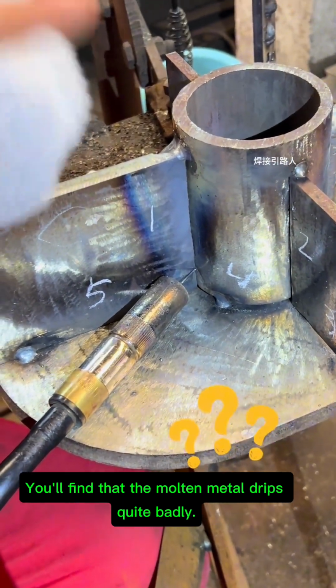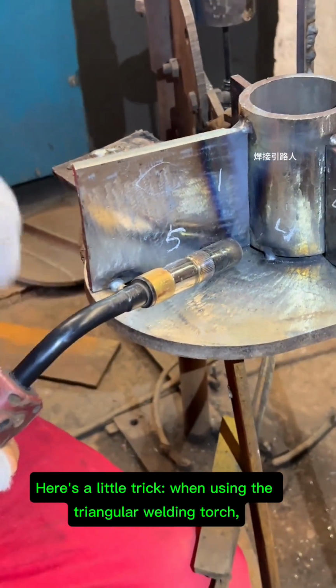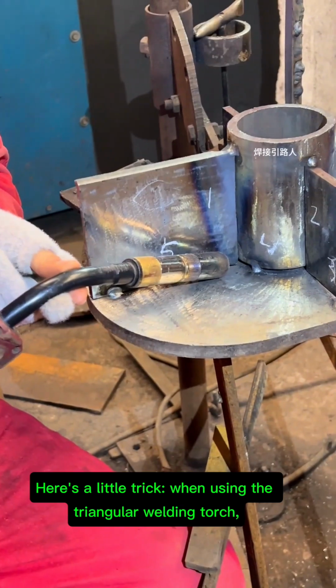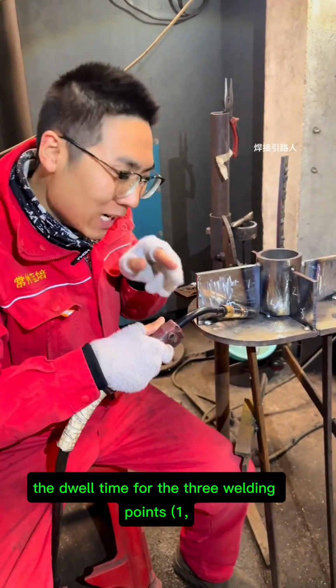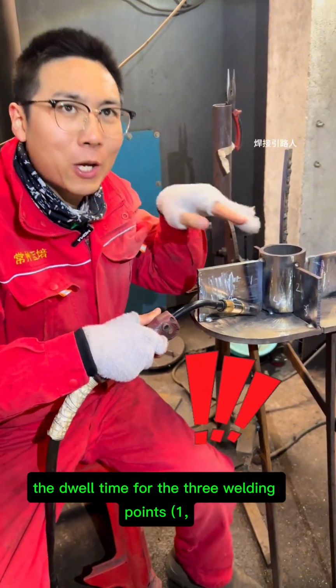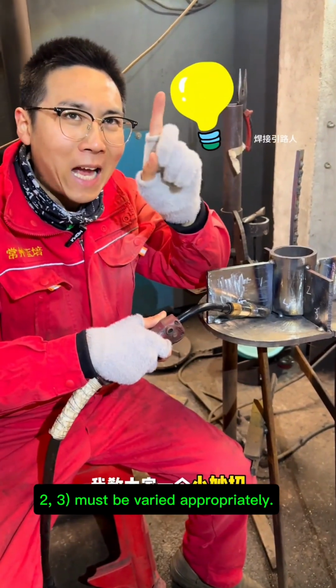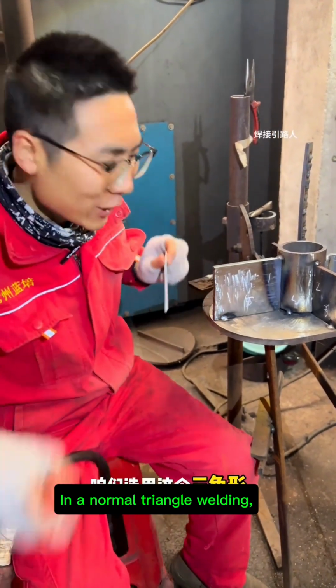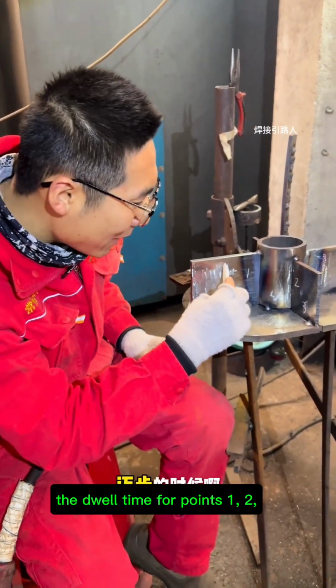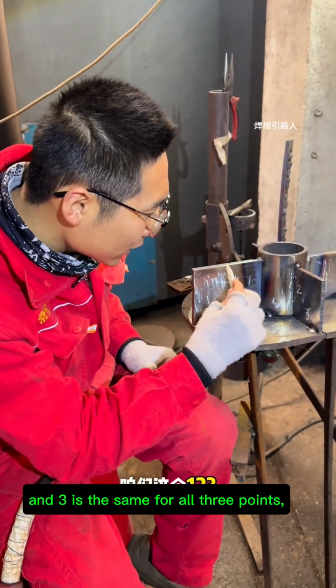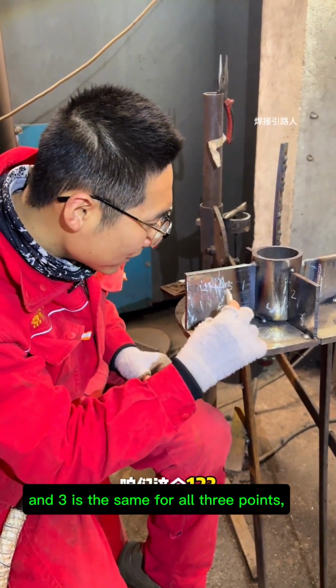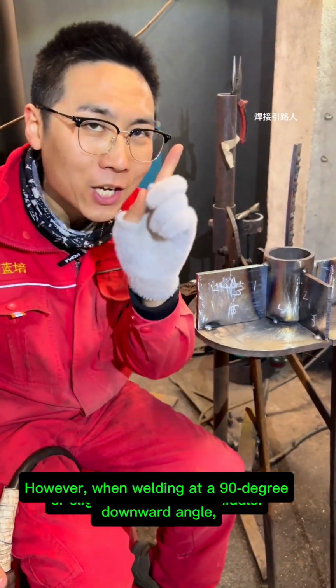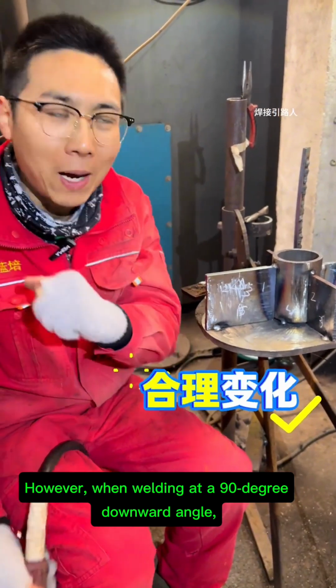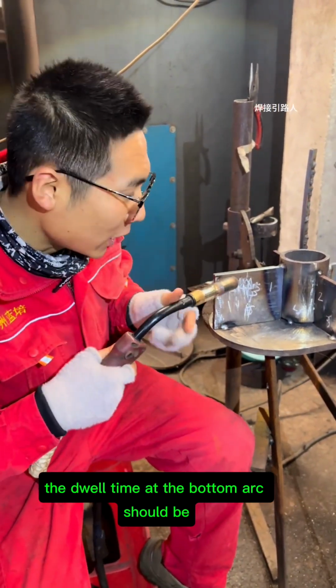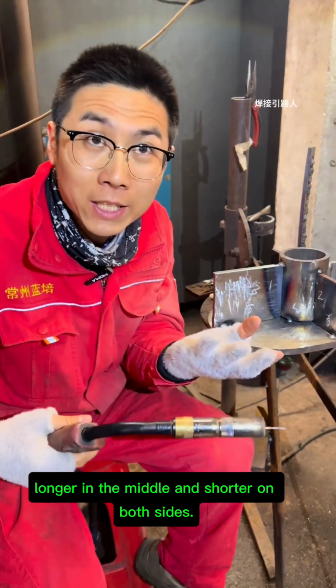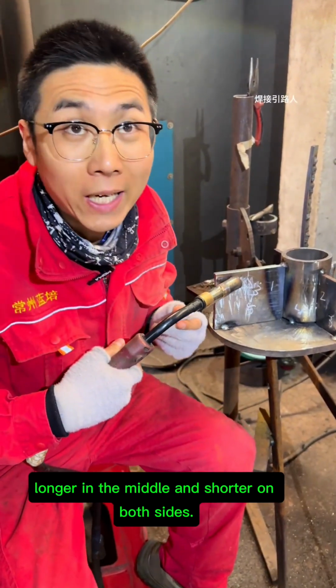You'll find that the molten metal drips quite badly. Here's a little trick. When using the triangular welding torch, the dwell time for the 3 welding points, 1, 2, 3, must be varied appropriately. In a normal triangle welding, the dwell time for points 1, 2, and 3 is the same for all 3 points, or slightly longer in the middle. However, when welding at a 90-degree downward angle, the dwell time at the bottom arc should be longer in the middle and shorter on both sides.